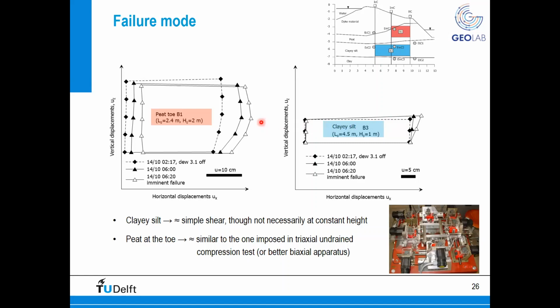So having an insight into the failure mode of the different layers in the field was extremely important for us, because with this information, we could also assess which type of test in the laboratory is more representative of the failure mechanism. So for a clayey silt material, we can assume that a simple shear, though not necessarily at constant height, is quite good enough. However, if you look at the peat at the toe, a direct simple shear test might not be the most suitable test for peat, because this lateral bulging could be better mimicked by a triaxial compression test, or even better, now we are placing a lot of effort in Delft into trying to use a biaxial apparatus to actually impose a plane strain lateral bulging inside peat.